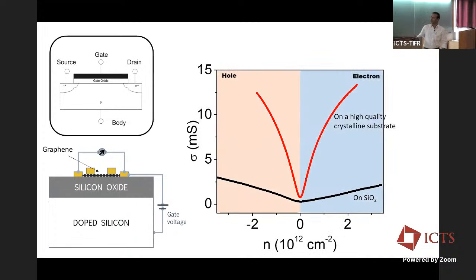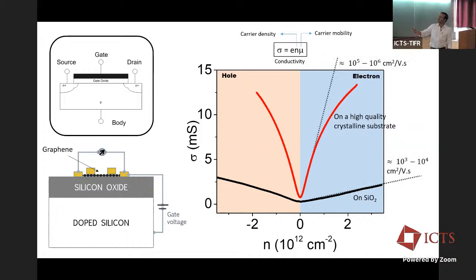So if I measure the electrical conduction in graphene, that is the conductivity from here to here, as the gate voltage, the voltage you put on this doped silicon, changes the electron density, then depending upon where the graphene is sitting, the conductivity shows a behavior something like this, which is called an inverted bell type structure. This is the part which is doped with electrons, and this is the part which is doped with holes. The conductivity is equal to the electronic charge multiplied by the density multiplied by the electrical mobility. In the case of graphene, the electrical mobility can be very, very high, nearly 10^5 to 10^6 centimeter squared per volt second, which is approximately 4 orders of magnitude larger than typical electronic devices. Silicon devices have typical mobility values in the order of a few hundred or so. So that's great.